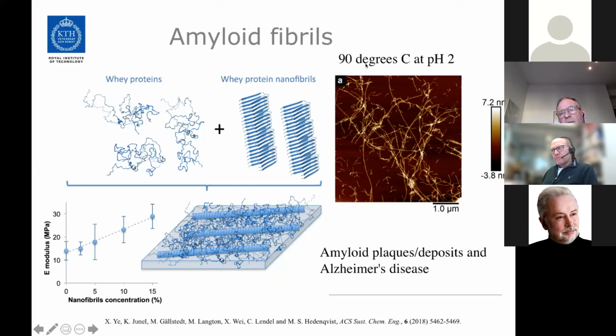You need a high temperature and a low pH, and essentially any protein you can start with. This is an example with whey proteins. What happens at these conditions is that the protein forms long threads with mainly beta sheet structures, which have improved strength. What we have been doing here is also an example of an all-protein composite. We take these amyloid fibrils and put them into a whey protein matrix, and you can see what happens to the stiffness as a function of the nanofiber concentration. So we are essentially stiffening the material with its own original material.